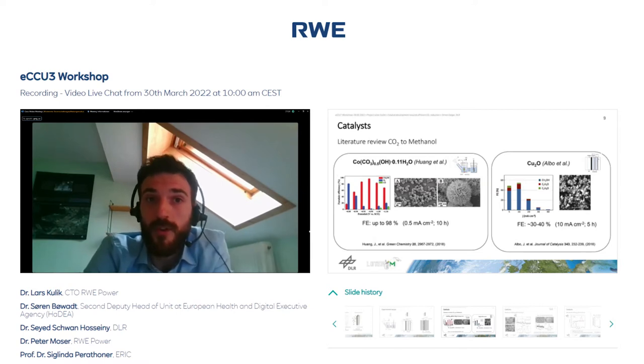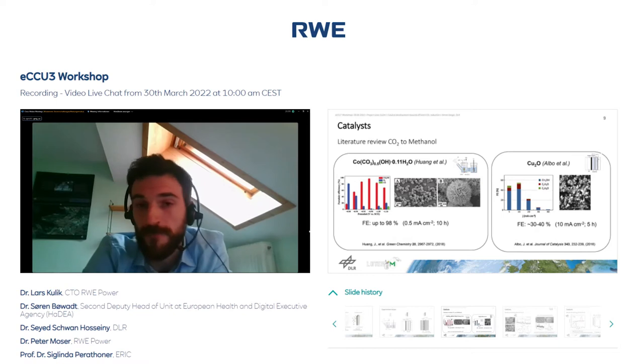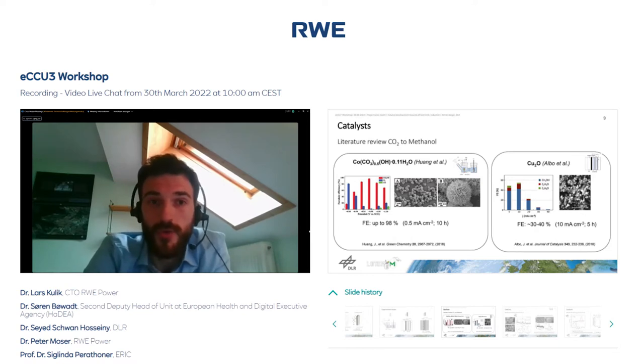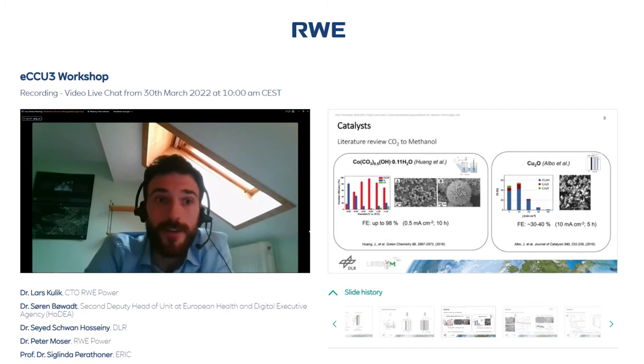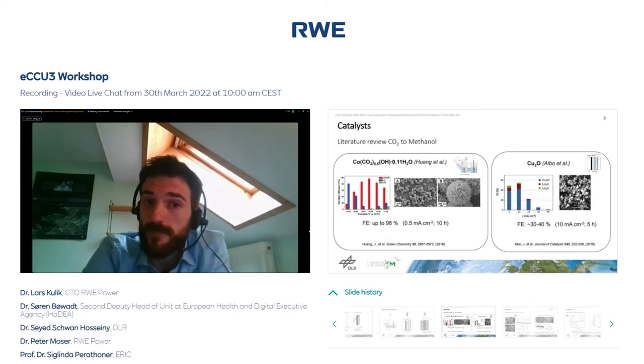On slide 9, we come now to catalysts. With respect to CO2 to methanol, which was the initial goal of this project, we had a look at the literature, checked different publications, and chose two that we would like to focus on. On the left side, there's a paper by Huang where they used a cobalt material that looks like these urchins that was capable of producing methanol from CO2 with about 98% Faraday efficiency. Faraday efficiency means 98% of all current that you put in would result in the product methanol, which is quite high in this case, but rather low current densities are used here. So we would reproduce this result and then scale this up to higher current densities in principle. On the right side, you can see a more modest Faraday efficiency of 30 to 40% presented by this copper oxide material by Albo, a Spanish group. And this was the second goal, to also reproduce this.